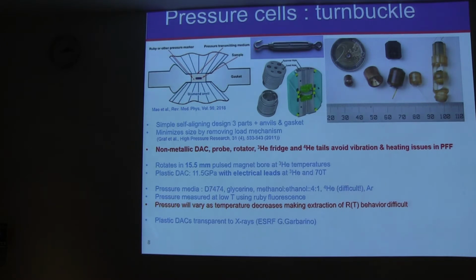This is a turnbuckle, and those devices are generally used to put wires or cables in tension. In that case, he used this principle to put two devices under pressure. He developed those two cups in which we put the diamond anvils, and if you have a really good machinist, you can ensure very good parallelism for your diamonds. Those two cups have opposite threadings: one has a right-hand threading and one has a left-hand threading.